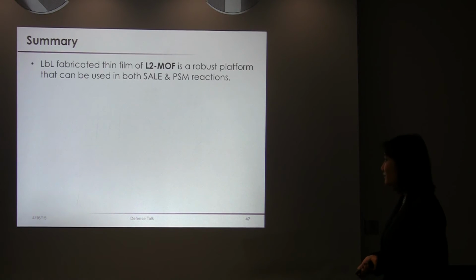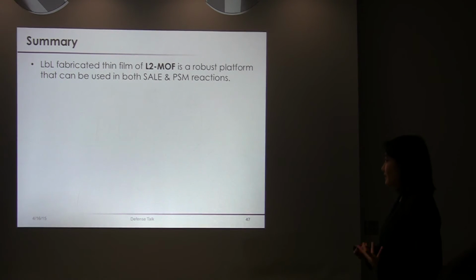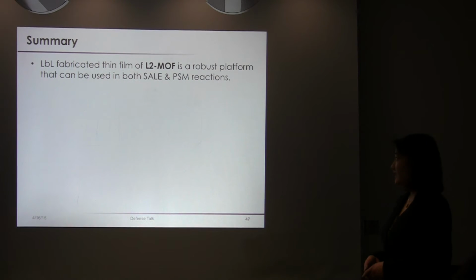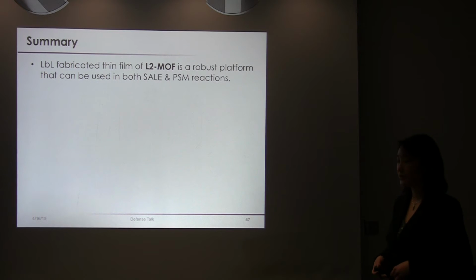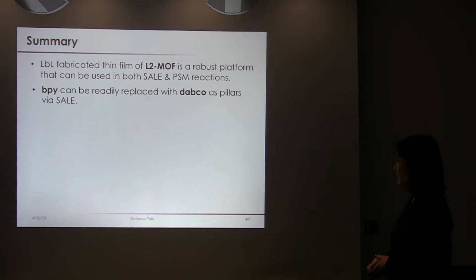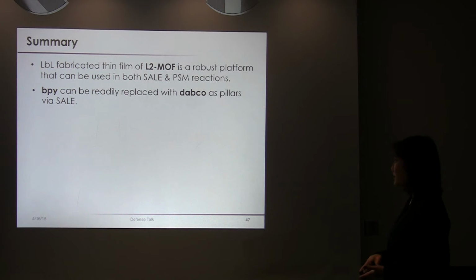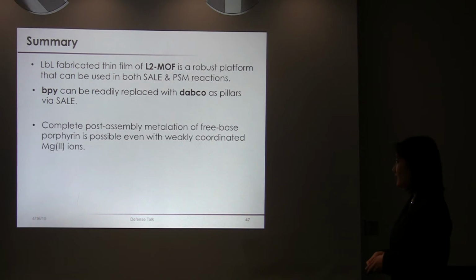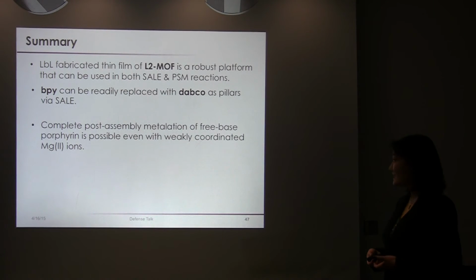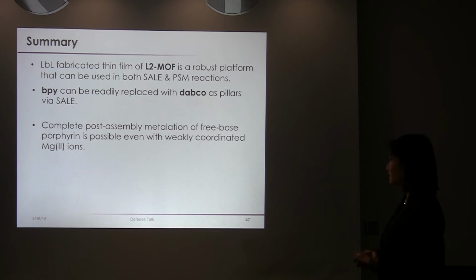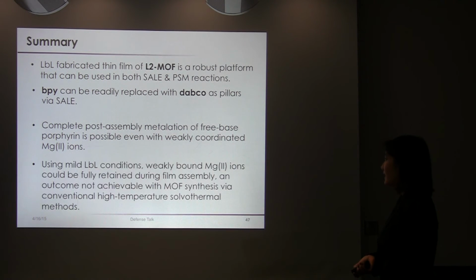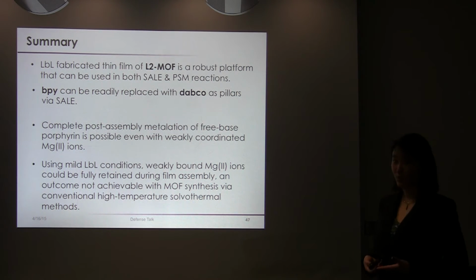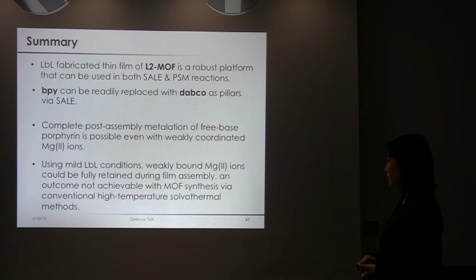So in summary, what I have shown you guys is that layer by layer assembled thin films of L2 MOF is a very robust platform that can be used for reactions such as SALE as well as PSM. And BIPY can be readily replaced by DABCO as pillars in a SALE reaction. Furthermore, complete post-assembly metallation of free-base porphyrins is also possible, even with weakly coordinating magnesium 2+ ions. And last but not least, using much milder LBL conditions, the weakly bound magnesium 2+ ions can also be fully retained during film assembly. And this was not observed in conventional solvothermal synthesis conditions.